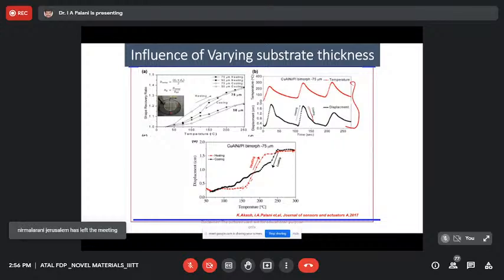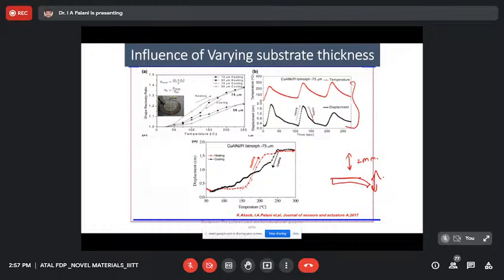Another option would be on a small intermittent level, where I need a higher order frequency. For example, if my displacement is around 2 mm, within this 2 mm I would like to achieve a higher order frequency. When there is a higher order frequency, I could see the overall behavior coming out of it, and basically I can predict my shape recovery from it. So this is one important aspect with respect to characterization of this shape memory alloy.